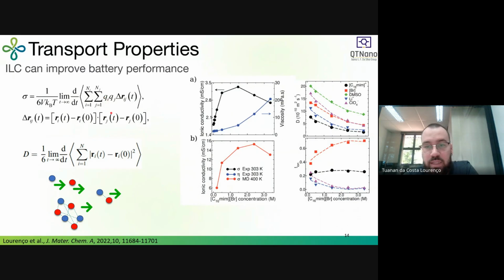So that means that to increase the ionic conductivity, two things can happen. First, my ions can be faster, so more displacement, or I can have more charge in the system. If I add more salt in the system, I'm adding more charge, I have more particles to carry charge. So when we add more ionic liquid here, we see the increase because we have more charge carriers in the system. However,